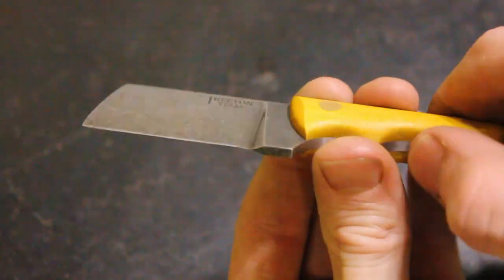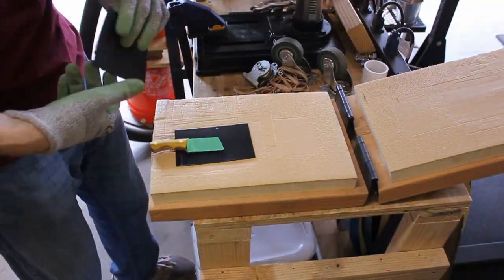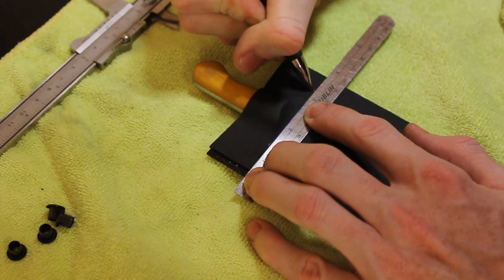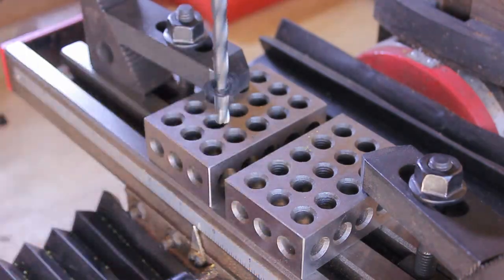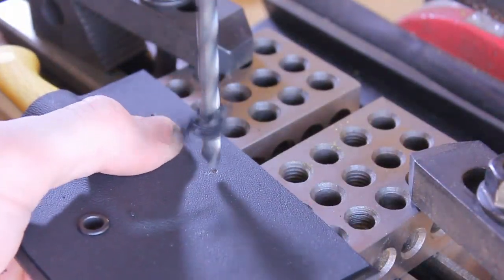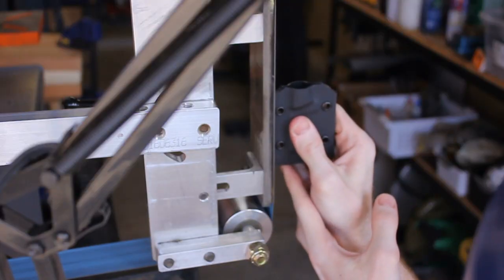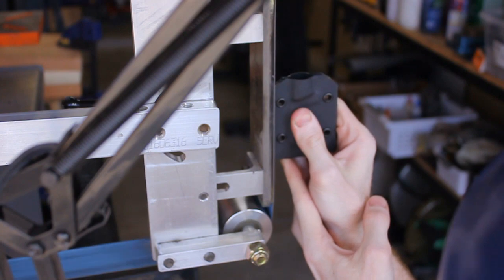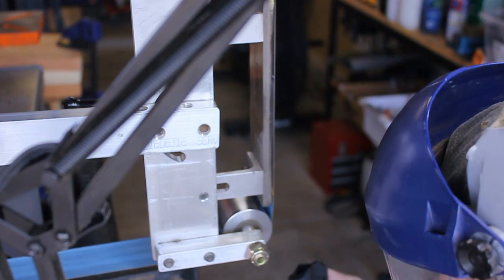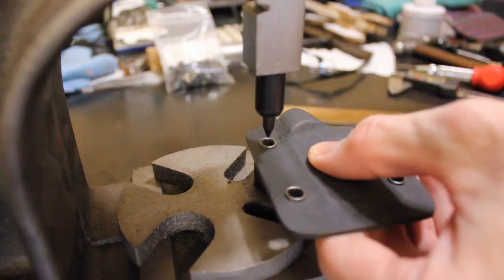For a neck knife we're going to need a necklace sheath. We've got two small pieces of Kydex, heat it up to around 285°F, smash it in the press, then mark out our holes and drill some quarter-inch holes for our eyelets. Side note: make sure you get your eyelets from a good American source - the Chinese eyelets seem to crush on me. A good source would be DIY Holsters. Those are actually their eyelet dies as well.